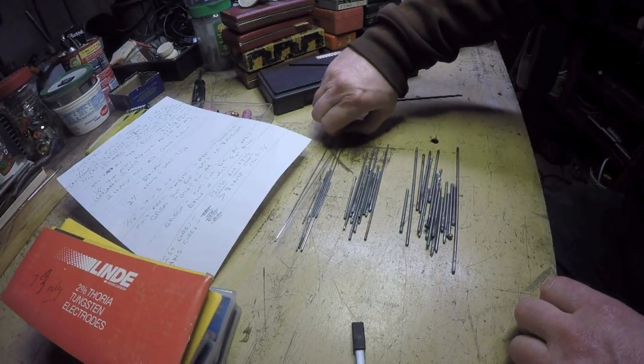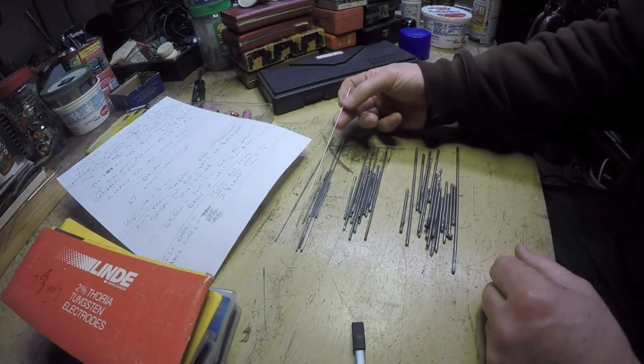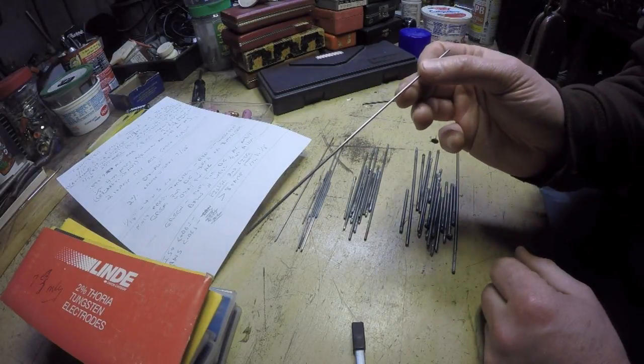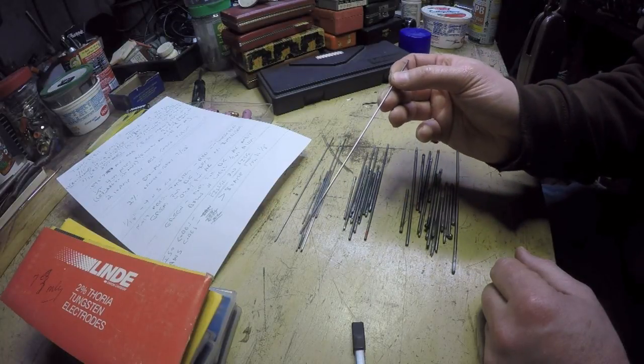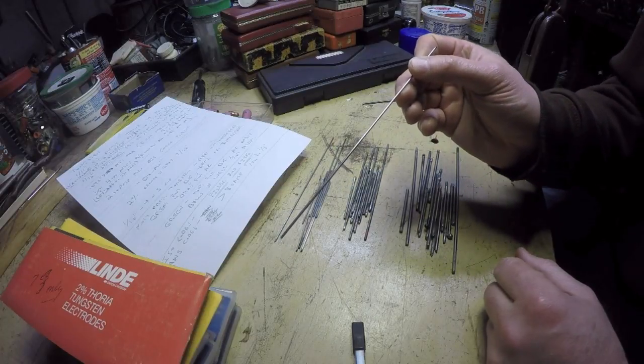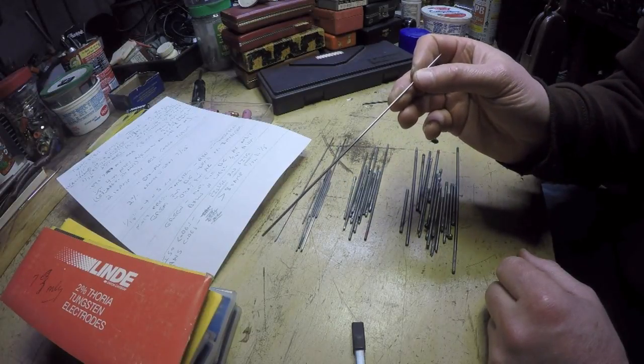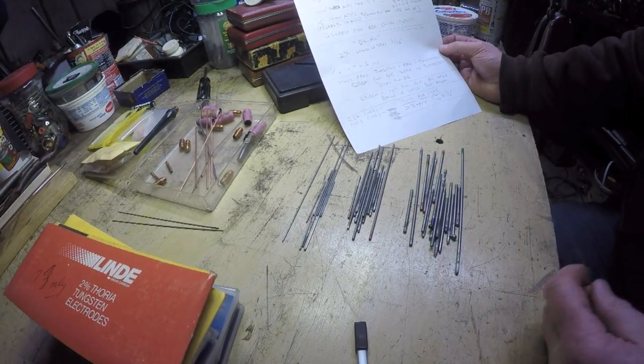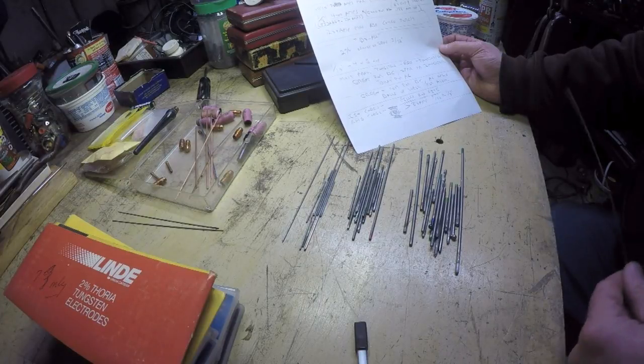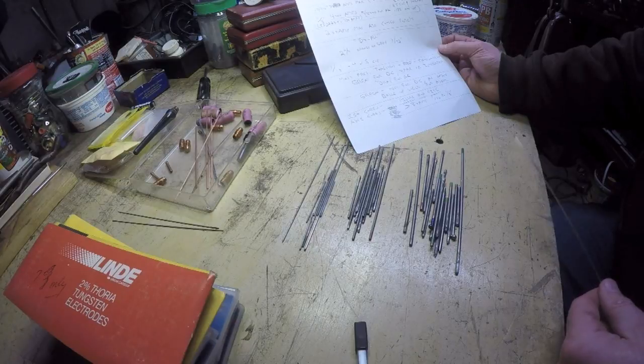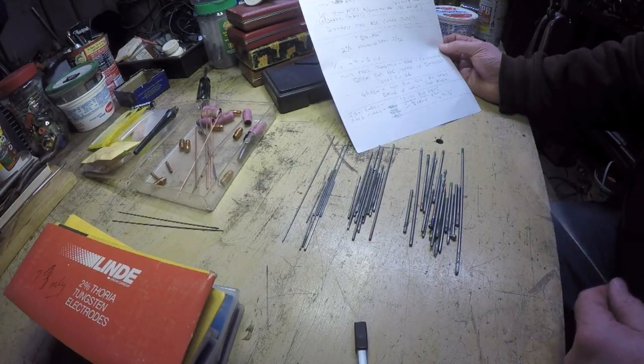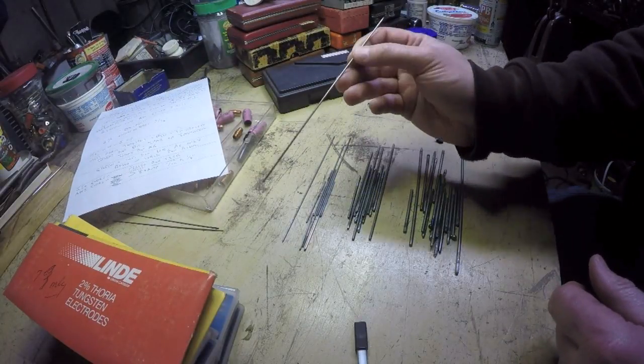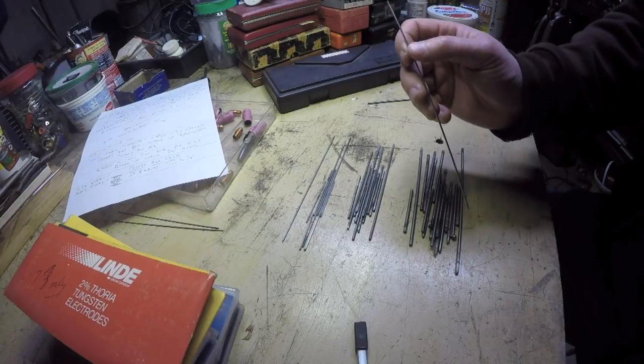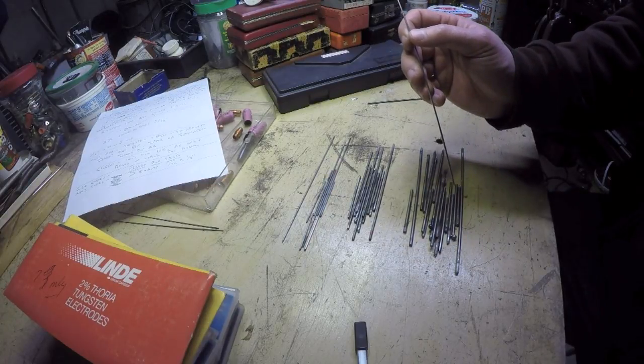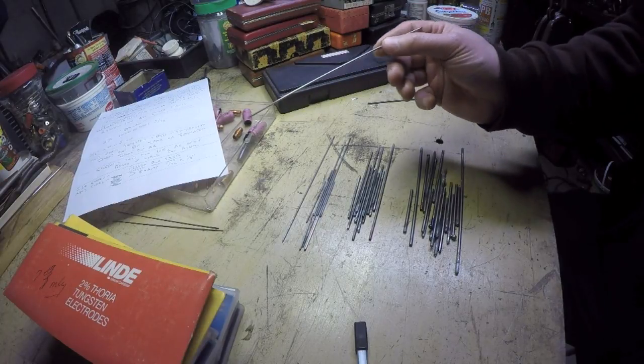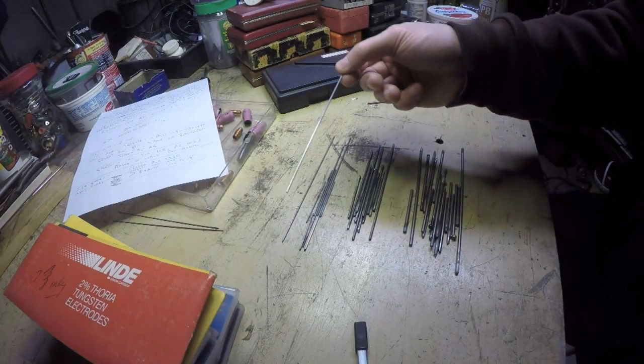So next up the food chain is the 1/16 of an inch electrode. Like I said, it's considered a common go-to electrode for a lot of people. And this electrode can easily handle up to 100 amps. Scratch that. I said 100 amps, but that was something I saw on one of the videos, and then later I saw that they actually talked about that being 150 amps max for a 1/16 inch electrode. And on the weld.com website, I've got a chart here for TIG welding parameters in mild steel, and that shows the current 100 to 140 for a 1/16 inch electrode.